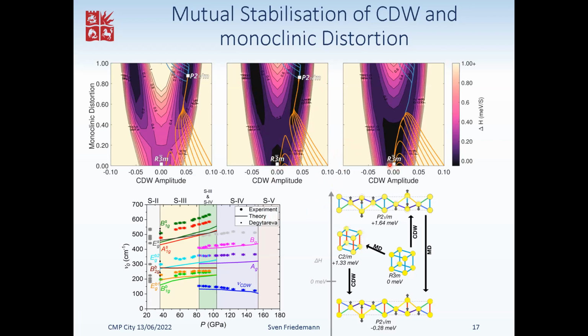But then you can see later on, for higher pressure still, the energy minimum is for no charge density wave and also no monoclinic distortion. So they are really coupled to each other. Okay. The fact that there are no data points above, I don't know, 150 something.